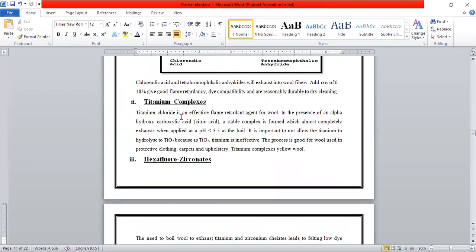Second is titanium complexes. Titanium chloride is an effective flame retardant agent for wool. In the presence of an alpha hydroxycarboxylic acid, a stable complex is formed which almost completely exhausts when applied at a pH less than 3.5 at the boil, and it is important not to allow the titanium to hydrolyze to titanium dioxide, because as titanium dioxide, titanium is ineffective. The process is good for wool used in protective clothing, carpets, and upholstery, and titanium complexes yellow wool.